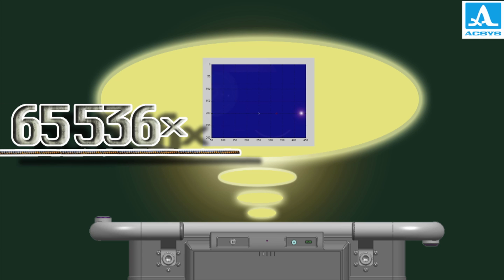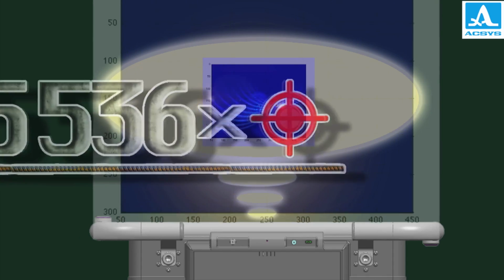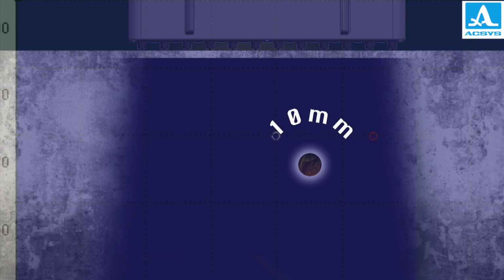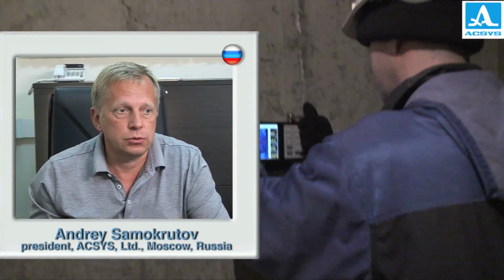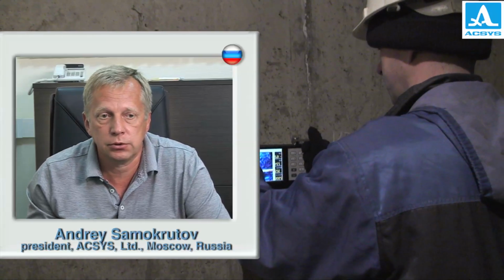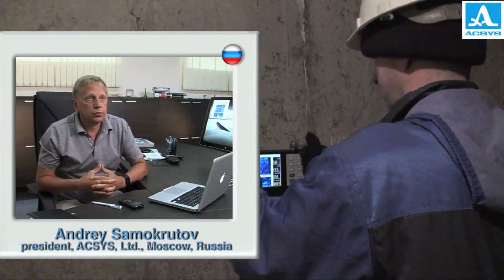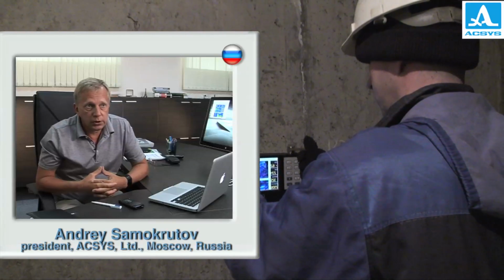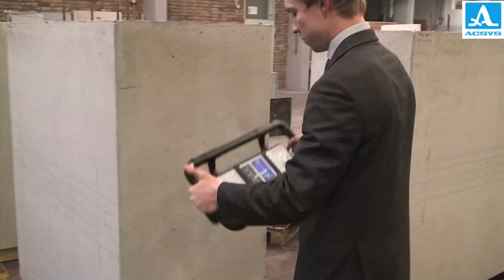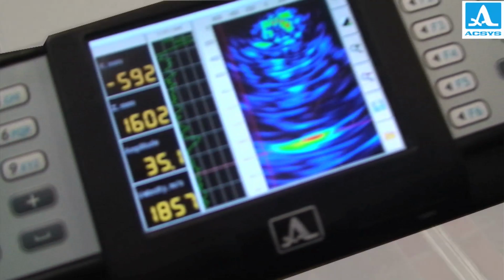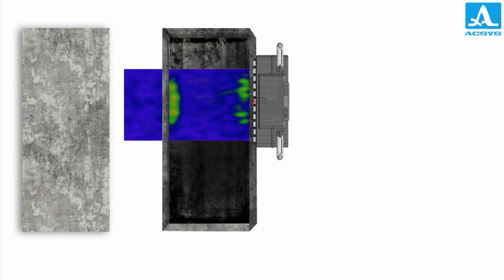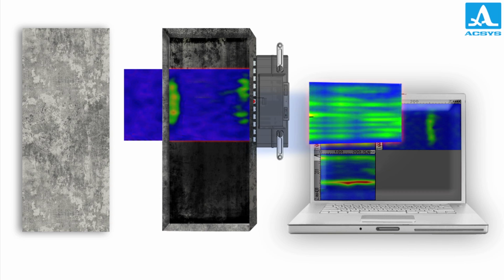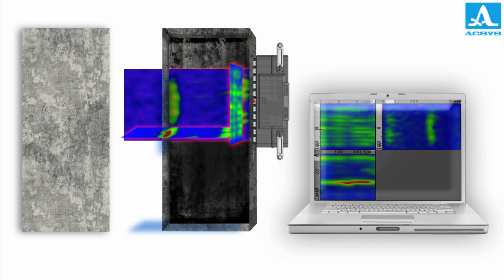The image is formed with more than 65,000 points by digitally focusing the ultrasonic pulse. The high resolution of the reconstructed images enables the MIRA system to locate flaws as small as 10 millimeters in size. By reconstructing the information from numerous transducers of the antenna array, a comprehensible image can be produced. Furthermore, a 3D image of the internal structure can be made with the help of the specialized software. The test results are shown as a typical B-scan, cross-sectional image of the area below the antenna along the plane parallel to the longitudinal axis of the antenna.